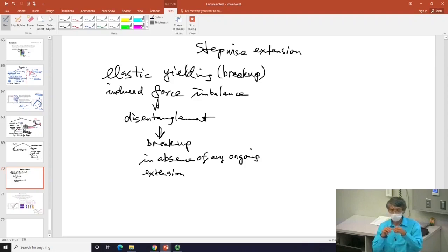This is something microscopic in front of you and big. I would apologize if I made a mistake, meaning if I missed something in the literature, but I think prior to our report, the knowledge of such a phenomenon doesn't exist: that after a large enough step strain, you hold it, it will break. Okay? Now, that's this side.